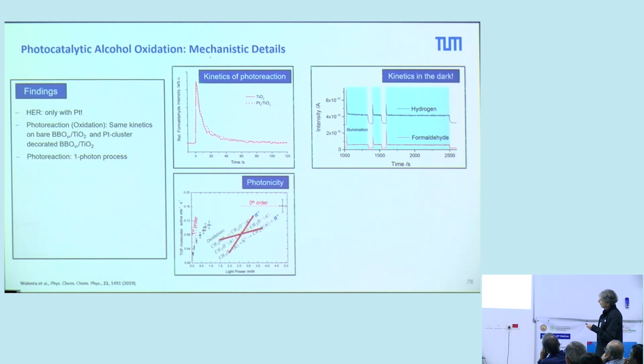And then, of course, we can also look at the kinetics in the dark. That means we can look at this behavior here, and I will discuss in the following what we can learn from this. But most important, you see that the formaldehyde is decreasing as soon as we turn off the laser. That means the charge carrier dynamics seems not to play a role. This is also something in photocatalysis. People often think that the charge dynamics is important. Here the kinetics is much more important than the charge carrier dynamics.